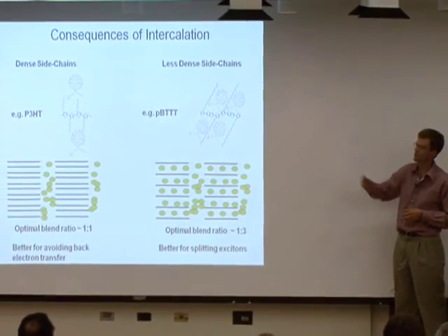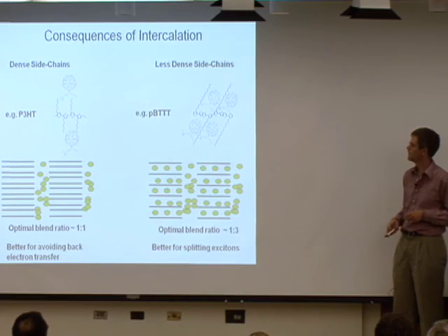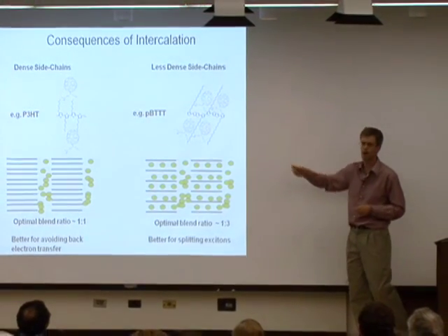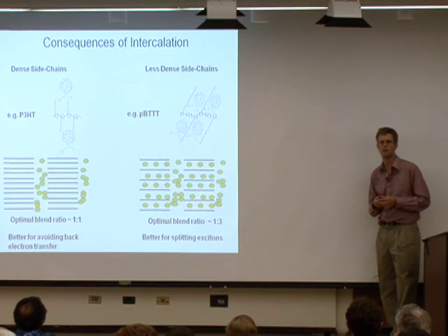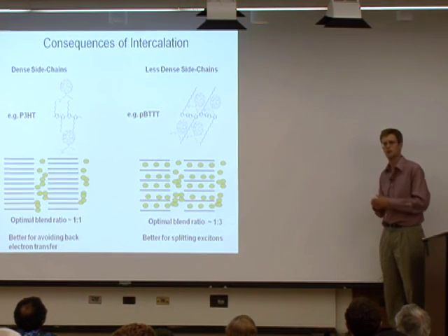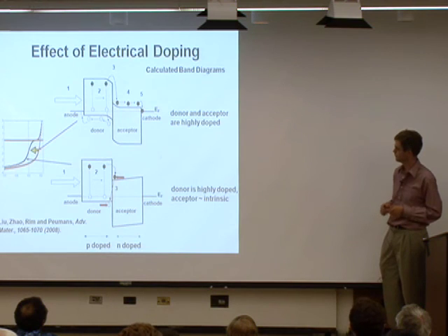So now I'll give you one highlight of Peter Peumans' work. So his approach is a little bit different. What he does is he takes molecules that are smaller than the polymers, and he evaporates them in a vacuum chamber. So a disadvantage is that you have to go into vacuum, but an advantage is he doesn't need these side chains. Those side chains are insulating, and we're forced to put them on to make the polymer soluble. So he can get away from that, and some of his molecules can have better properties, but perhaps the processing is a little bit more expensive.